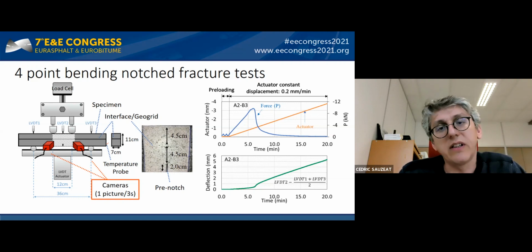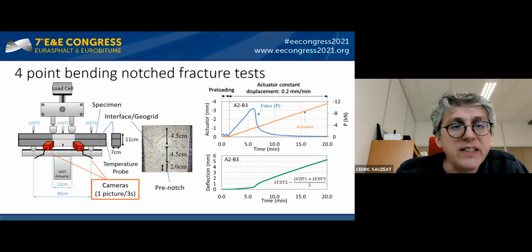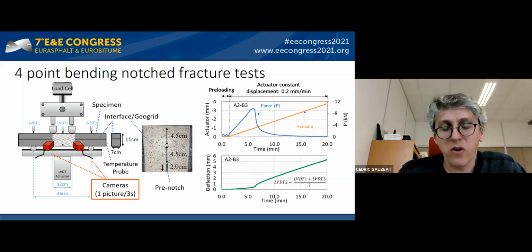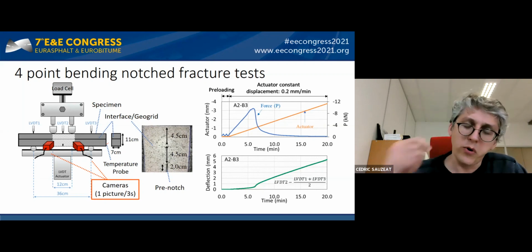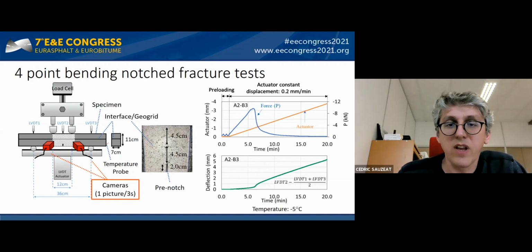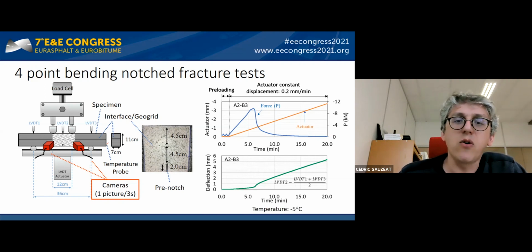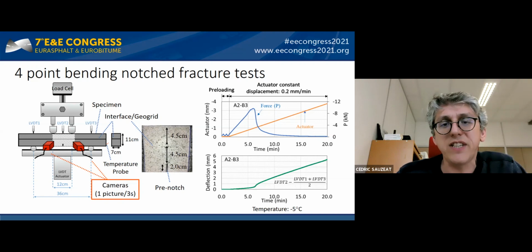3 LVDT sensors. These 3 LVDT sensors enable us to correct the punching effect that could appear close to the load application. The temperature was maintained during all the tests at -5 degrees Celsius.